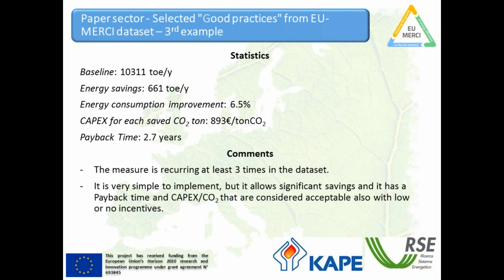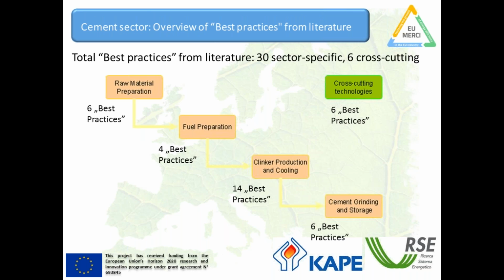But the capex is not very high over the CO2 saved, and also the payback time is considered acceptable for most industry investments, and so this is a measure that could be put in place also if the incentives were lower or there were no incentives, like in some cases that we found. For pulp and paper and glass, this is it. I think that Pavel can take the microphone and speak about the cement sector.